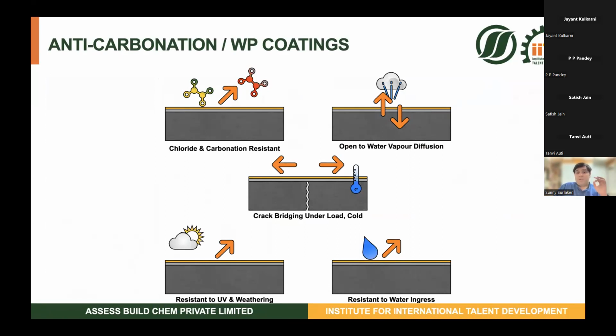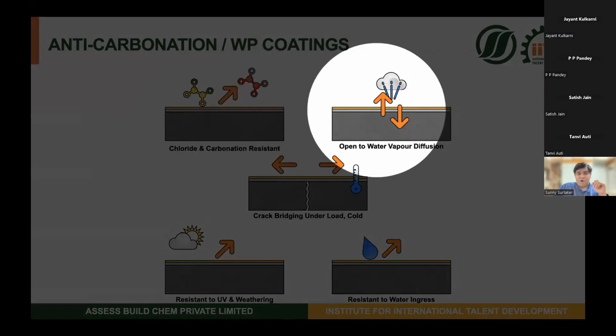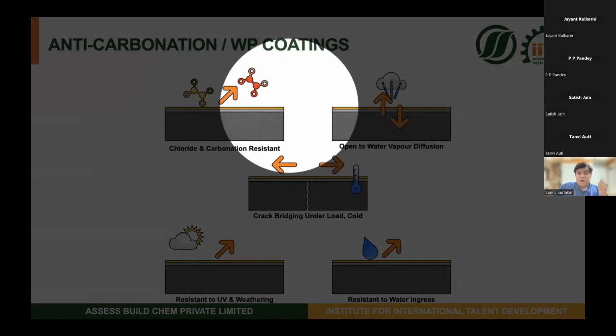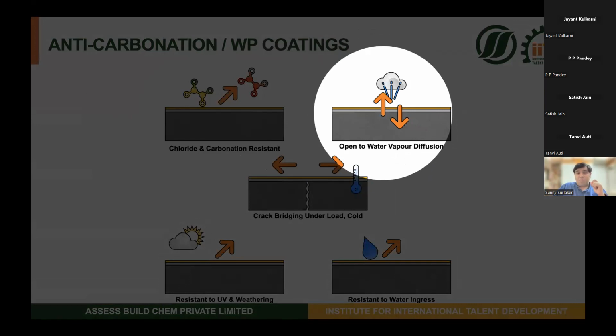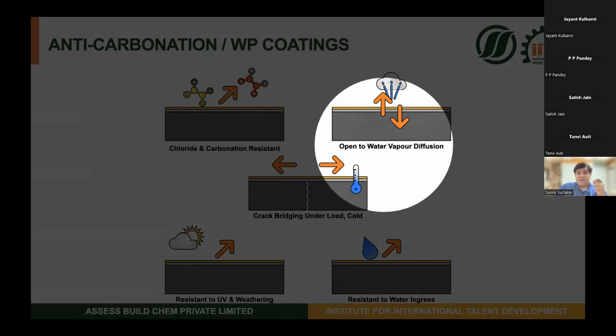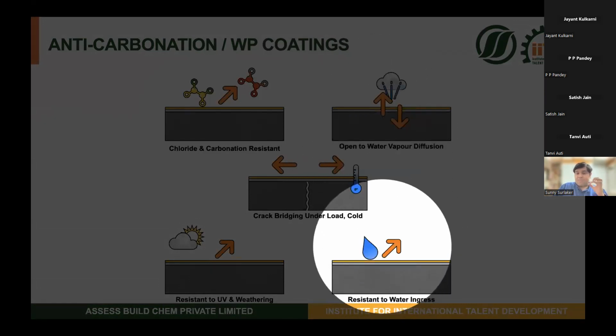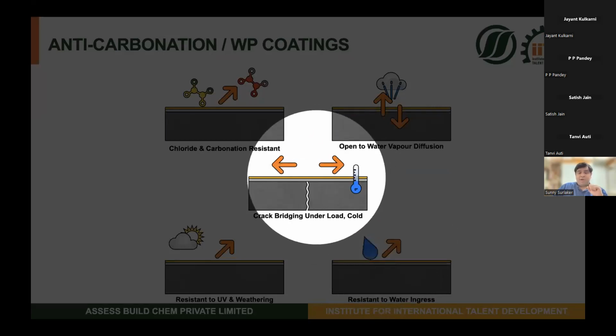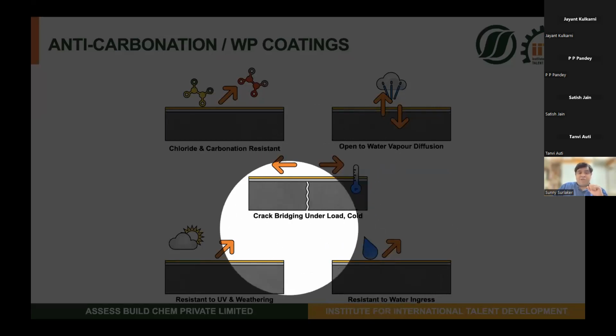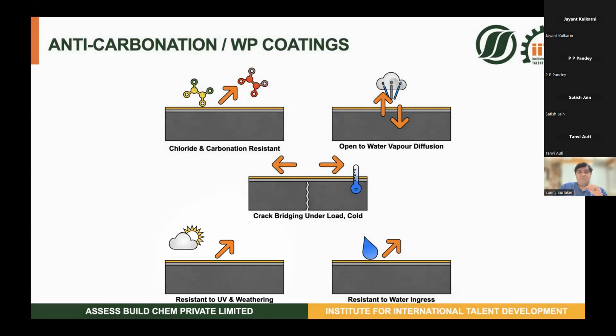Now, the best part about these coatings is that they have a lot of these properties put together. They are chloride and carbonation resistant. They're open to water vapor diffusion, which means they are breathable, as we call it. Of course, by default, they're waterproof. They're resistant to water ingress. They're very good with crack bridging and also resistant to UV and weathering. This is a type of material that looks and feels like paint. When you're processing or applying it, it feels like paint. But the protective quotient, or the life of this coating, is definitely much higher.